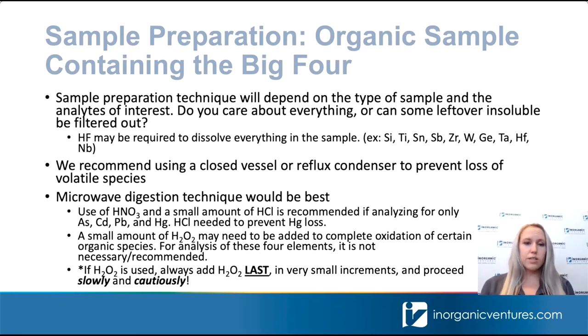Nitric acid is going to dissolve any of these materials for those four particular elements, if those are the only ones you're analyzing in your solution. And the HCl is just to stabilize the mercury in the solution. So one additional component that may be necessary depending on your particular analysis is hydrogen peroxide. That can help oxidize the rest of the organic species in your sample.